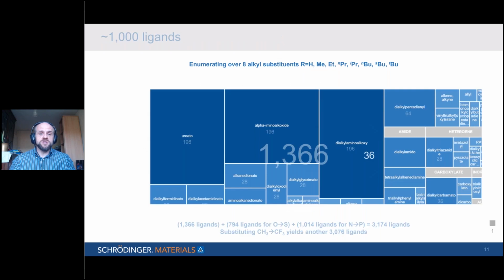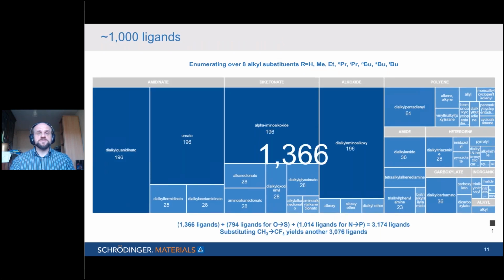If we now look at all the different families that I mentioned there, and enumerate over the R groups, over the alkyl groups, we straight away get up to well over 1,000 different possible ligands. So it's quite a large space. If in addition you substitute sulfur for oxygen, you can get another 794 ligands. Substitute phosphorus for nitrogen, you get another 1,000 again. Easily 3,000 ligands. Maybe substitute trifluoro for methyl, you can double the number again. So very easy to get up to large numbers of ligands that we have to consider in the chemical space when we're designing a new precursor.